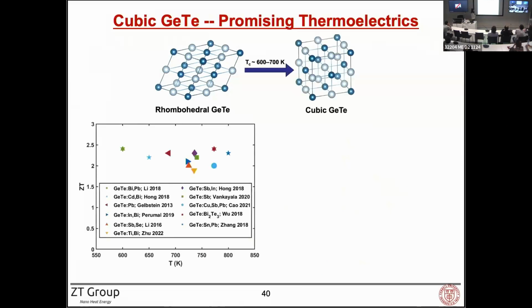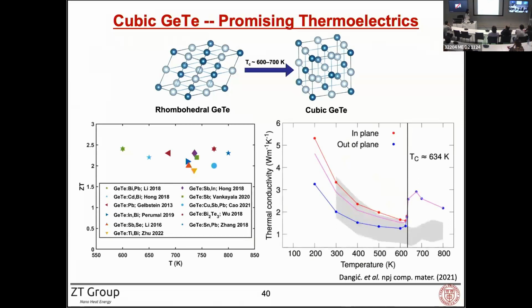So one of the motivations was from thermoelectric applications. We can see the cubic germanium telluride shows pretty high ZT values. This material has also been studied for phase change applications. And so we looked into the literature for the thermal conductivity. So we see, okay, before the phase transition, it seems like the previous calculations were able to pretty much capture the experimental trend, but not so much above the phase transition. So we wonder whether we can do a better job in terms of the computation to really close this gap.